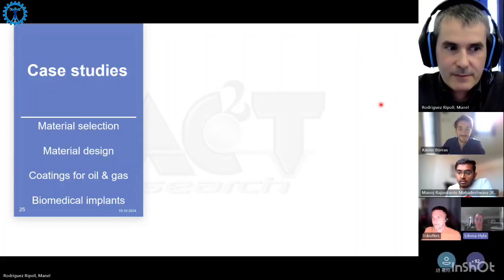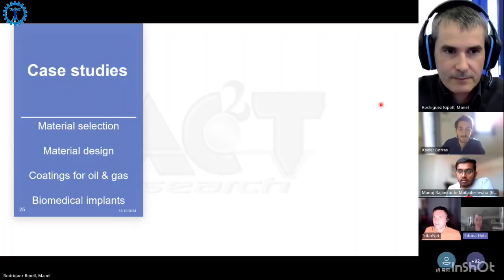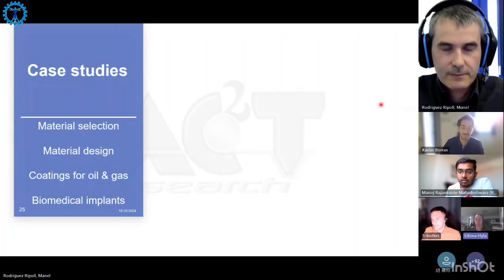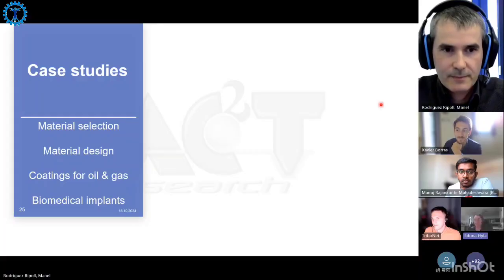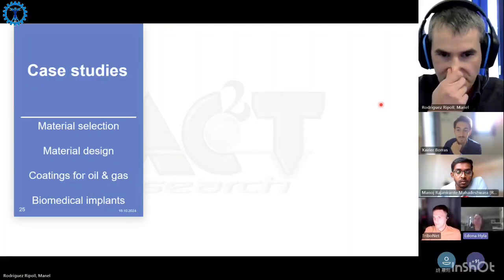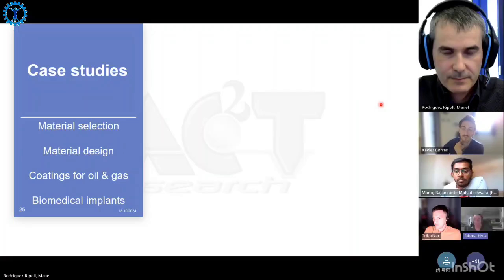I do some work related to tribocorrosion, and I'm using potentiostatic methods. So basically, we want to calculate the wear due to corrosion and the wear due to mechanical wear, and separate them. I'm doing similar to Michelin tribocorrosion on cobalt chromium for hip implants. What I've seen is that when I leave it for 30 minutes to settle the potential before I'm rubbing the material, sometimes it doesn't settle at the same corrosion range. Because my contacts are so small, the difference that it makes where it settles is huge between samples. So how can we avoid that our total volume wear due to corrosion has massive differences just because it settles at different potentials?